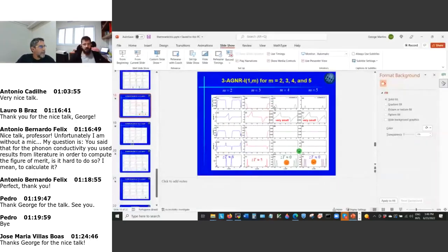Yeah, it's as I said, it's very hard to get intuition about this business, because all these quantities come from those integrals, and you have to do that integral for each one of the values of mu that you want. So each one of these curves here, I don't know what was the resolution that Patricia used in the mu here, because the horizontal axis here is mu for all the graphs. So yes, it's exactly what I said. You have F1 minus F2, which is approximated by the derivative of the Fermi-Dirac function, a delta function around mu. So this sets a window where you are looking when you do this integral.